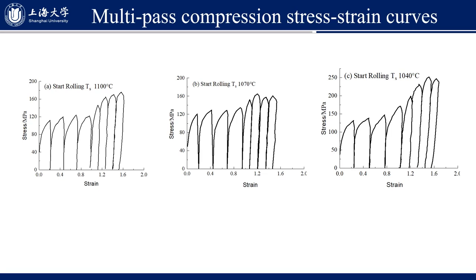This slide shows the stress strain curves of multi-pass compression test specimens with different start rolling temperatures, say 1100 degrees C, 1070 degrees C, 1040 degrees C. We can see different stress strain curves of the steel obtained.